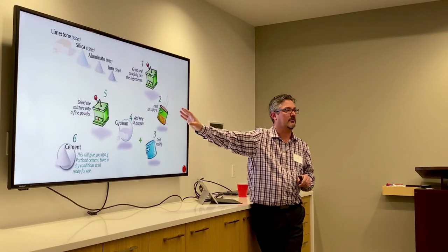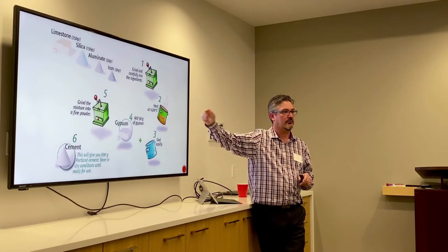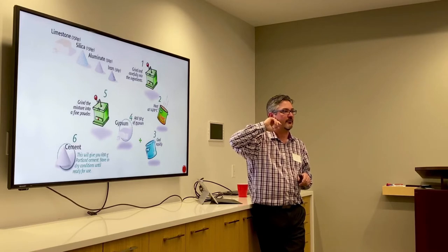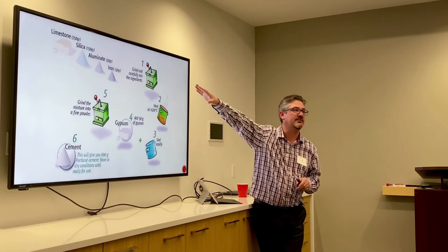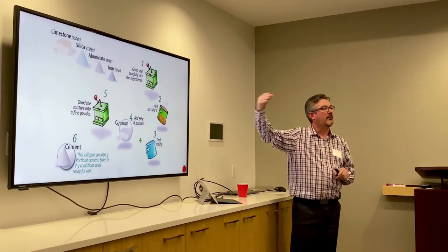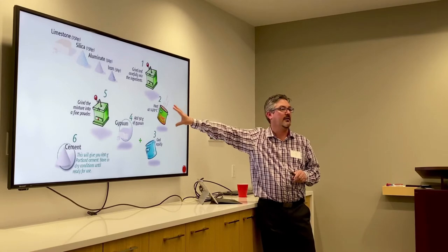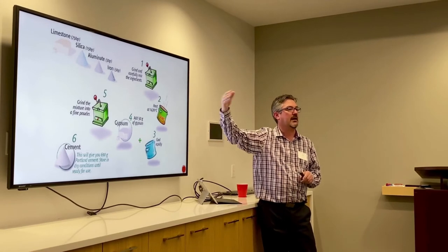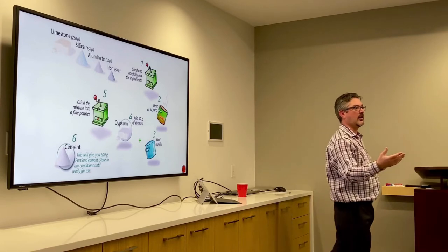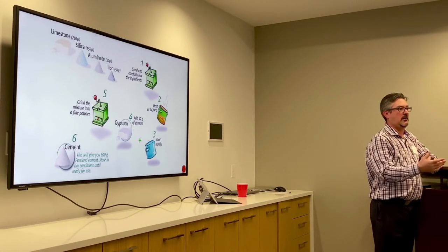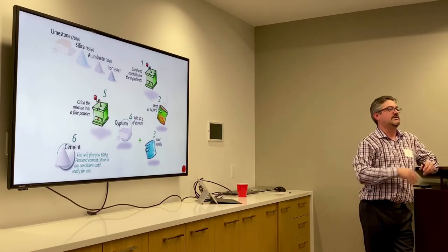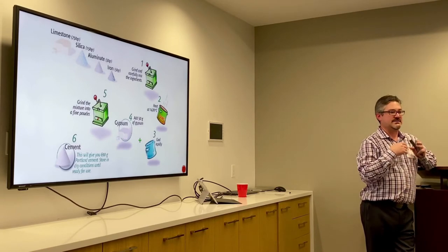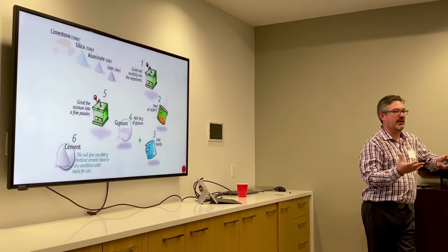So where did the extra weight go? CO2. So why does the cement industry produce all this CO2? Any ideas? Calcium carbonate reduction. So limestone is predominantly calcium carbonate. The first step that is undertaken in the heating process is to actually reduce that calcium carbonate, drive off the CO2 from the calcium carbonate to make calcium oxide. That is then chemically bound with other materials like the silica, the alumina, and the iron to make calcium silicates, which is the glue that binds all these rocks back together.